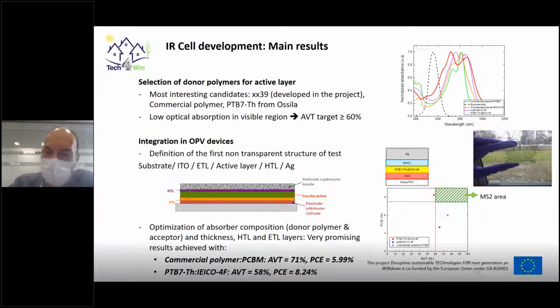and also the thickness. At this moment, we have achieved very interesting results using the commercial polymer in combination with a PCBM acceptor, which has allowed us to obtain very promising values of transparency, as high as 71%. This corresponds to this value here in the plot, with a conversion efficiency of about 6%. For the other material, the PTB7 material that was identified, in combination with the IEICO-4F acceptors, we can obtain a much higher efficiency. This is very interesting. The efficiency value is 8.24%, which is even higher than the target efficiency in the project, even if the transparency is lower. We are just below the 60%, at 58% transparency.